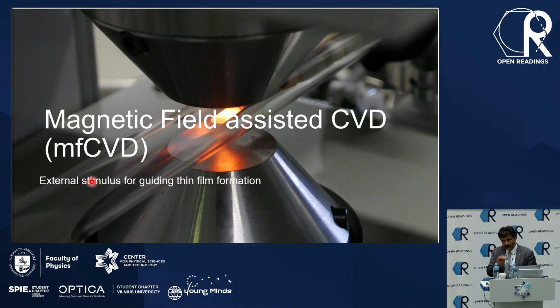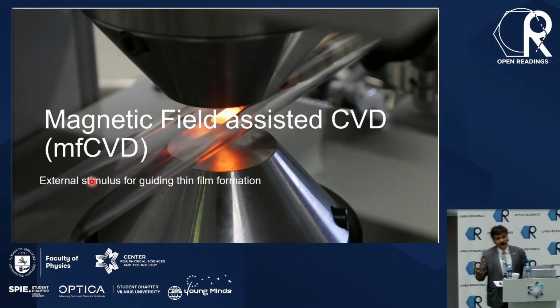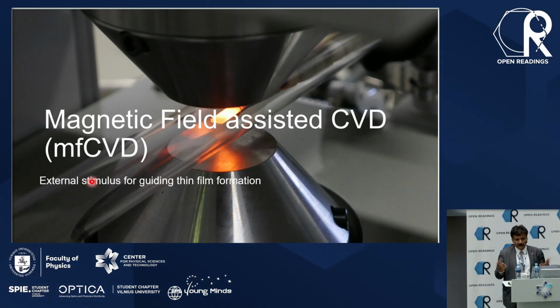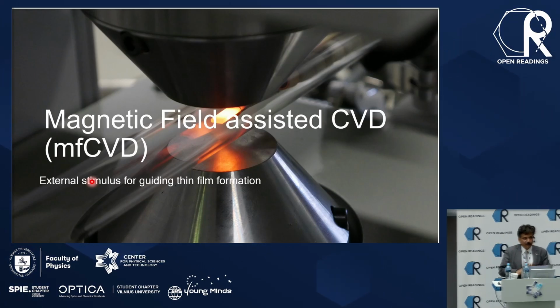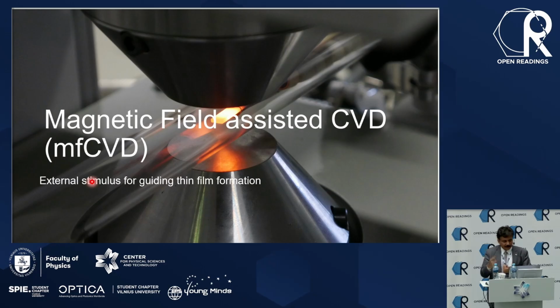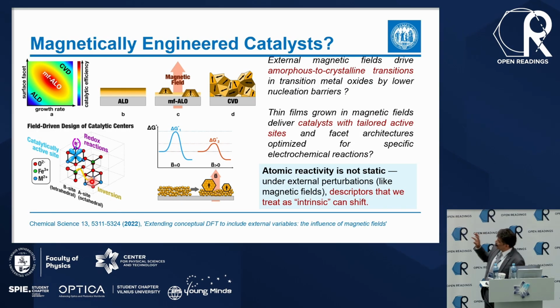One thing is to make materials now in a magnetic field or field. We do synthesis in our typical parametric space using temperature, using pressure, using different solvents, microwave. Field has been less used. So we applied a magnetic field because iron oxide is antiferromagnetic, but it still has iron 3, which is a d5 center. And what we found out is that by applying a magnetic field, you can control a lot of things in the material. You can control the atomic scale ordering. You can promote certain facets on the surface. And that is something which is helping the catalyst to survive for a longer time. I will show you the example.